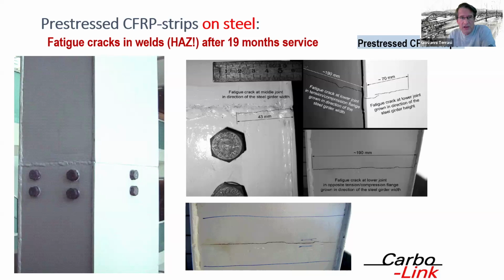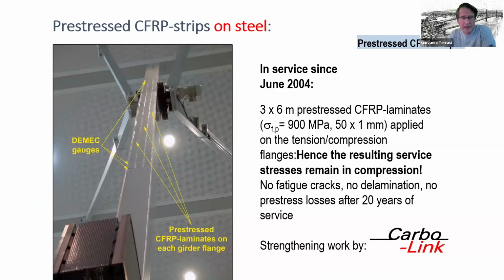And we came up with pre-stressed, externally bonded Carbodur CFRP pultrusion plates, which, on the next slide please, were applied on the top and bottom flange, so tension and compression flange, over 6 meters, anchored in low-fatigue areas. They were pre-tensioned and applied in a pre-stressed state to pre-compress the welded steel girder, in order to shift the bending stresses to pure compression at the level of the butt welds near the pivoting drive section.